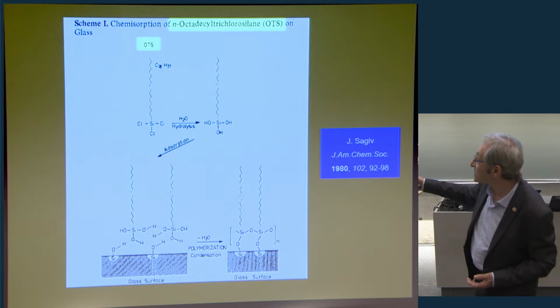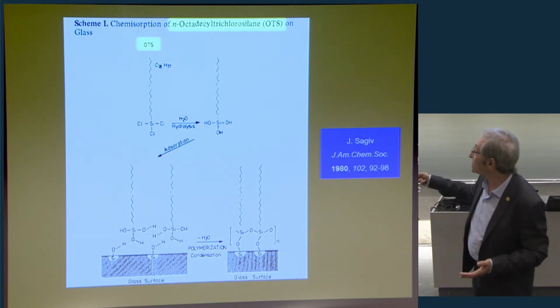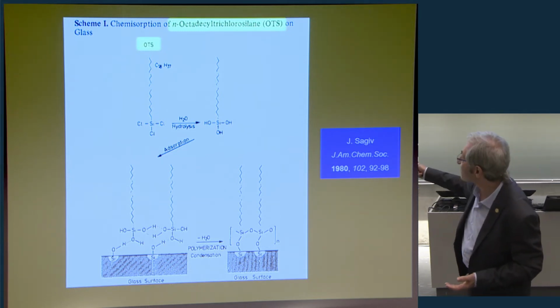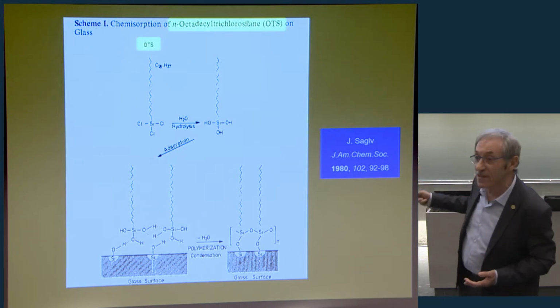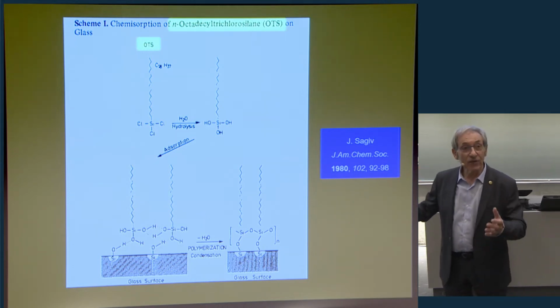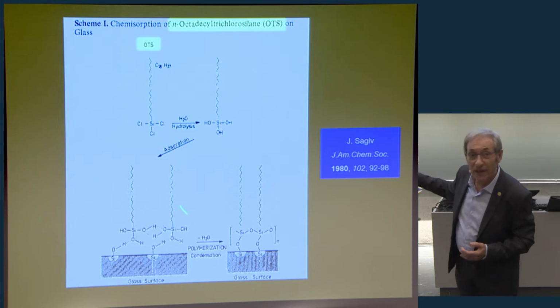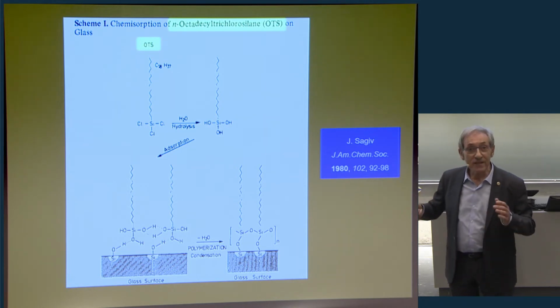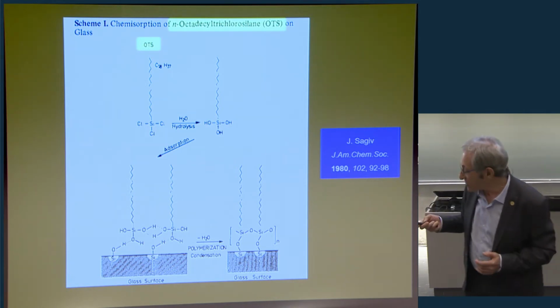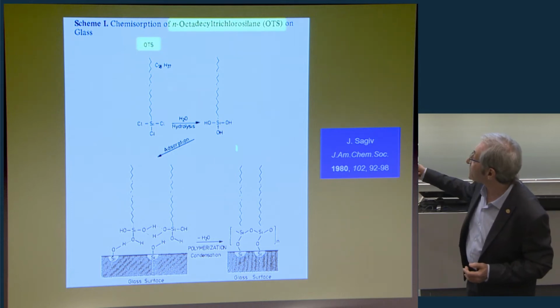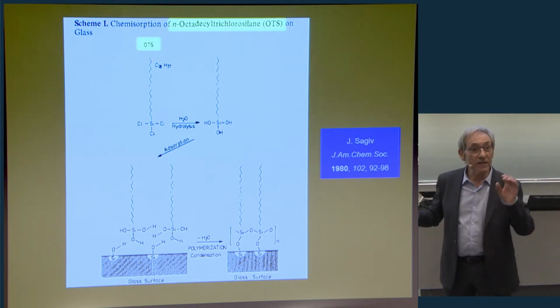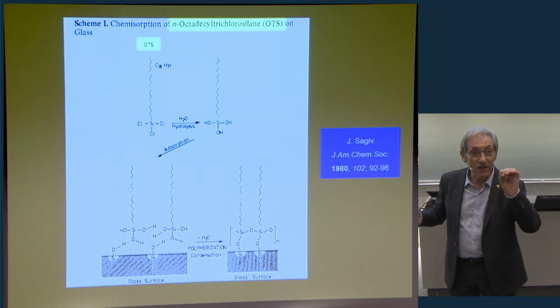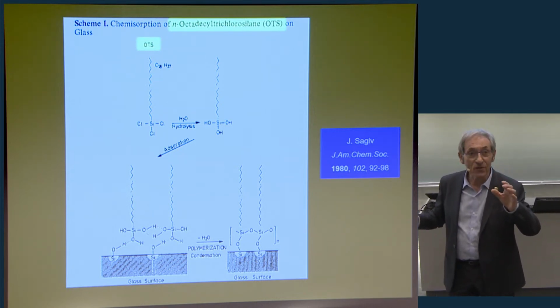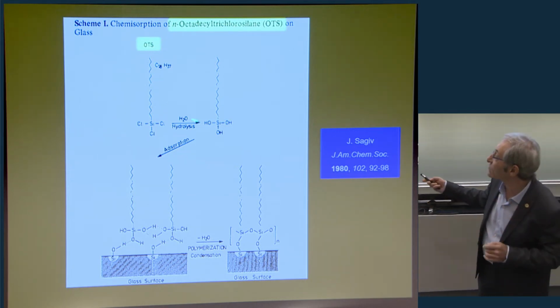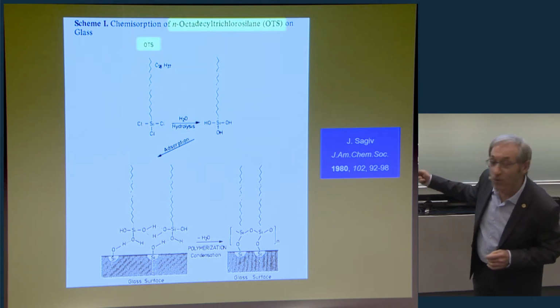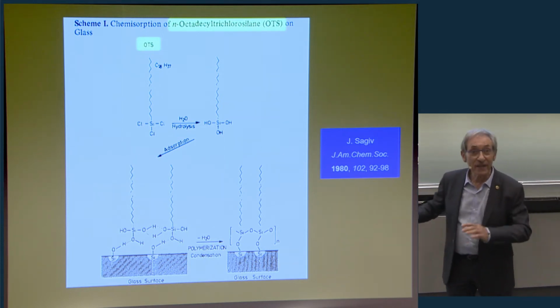This is a glass surface, and this is very important. You see, the silicon of the molecule is actually the same silicon as the silicon of the surface. So then you get a direct binding of something organic to the surface. But this is an extremely complex process, because of the water. This is a very important word: where is the site of the hydrolysis? If you have too much water in solution, the hydrolysis will occur in solution, and then you may get polymerization of this material, and you get a mess.